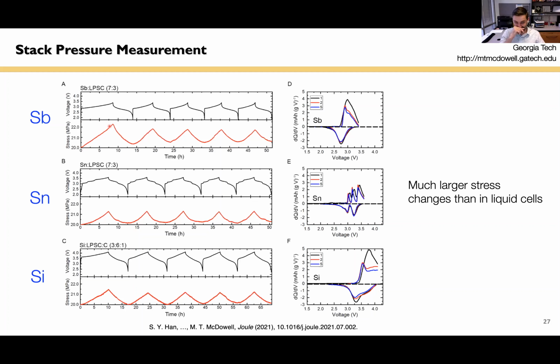So this is interesting because it's either a problem, because this would be a significant change in stack pressure in reference to the baseline, or is a potential opportunity, because what we're showing here is that the materials themselves can effectively apply a stack pressure in a constrained environment that's on the order of what you need to enable good cycle life. So I think that's an interesting piece of food for thought.